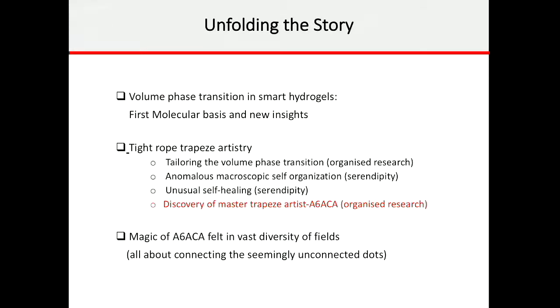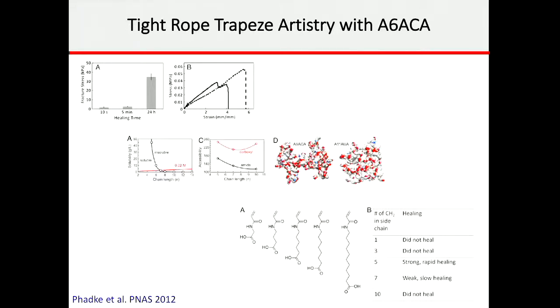Now, this is where the discovery of the master trapeze artist came up. Because we kept on doing these experiments, by the way. We also did some very advanced sort of molecular dynamic simulations, which you see here. And the basis was that as we kept on playing around with the number of methylene groups, if you had just one, there was no healing. 3, no healing. 5, strong and rapid healing. 7 was weak, and 10 did not heal. So if you had too small numbers, it did not heal. Large numbers, it did not heal. But there was a magic about 5. That means acrylyl 6-amino caproic acid.